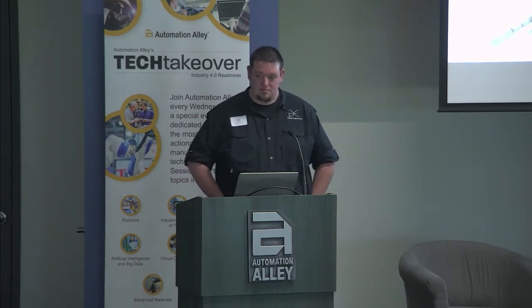A key thing to know is that the performance of the material is going to be basically the same as if the part had been injection molded. The material properties of nylon 12 are pretty well documented. And then the question is, how badly does the manufacturing technology mess with that? The good news is that the material properties are very strong. If the part had been FDM, which is filament printers, you'd probably have an issue with layers. If you had sintered the part rather than fully fused it, it might not perform as well. But if that material works well in an injection molded application, it should work fine if it's been manufactured using multi-jet fusion.